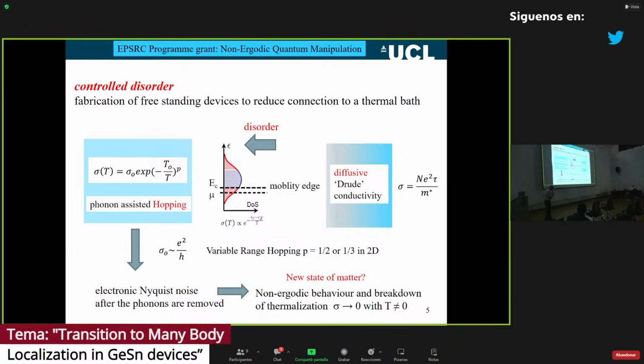And there's a second type of hopping called Efros-Shklovskii, which is slightly more sophisticated. When the electron hops, or the hole hops, it leaves a hole, or the electron would leave a hole, and it gets bound to that hole. But it has a slightly different energy because it's bound to that hole. So it kind of creates an excitonic state, and that shifts the energy of the system. So when we're in this hopping regime, what is interesting is that this prefactor to the conductivity here is e²/h. So it's just the quantum of conductance, but the system is thermally assisted.